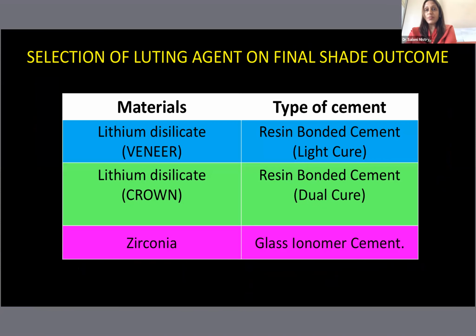Now let's look at the brief. When you're using lithium disilicate for a veneer, then obviously you can use a light cured resin bonded cement. When you're using a crown, that is a full veneer crown, then you're going to be using a dual cure, because obviously in a full veneer crown, the thickness is probably 2 millimeters, and the light penetration is difficult. So that's why it is important to use a dual cure resin cement.